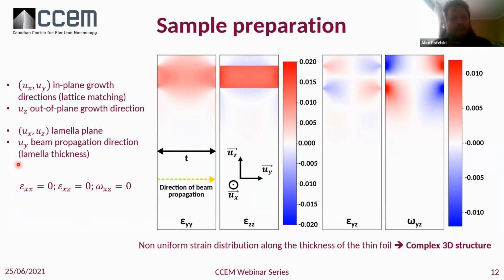As I told you, in plane along X, so perpendicular to the pillar, there is no deformation, no shear, no rotation. And we're going to use the following notation throughout the entire presentation. We're going to call UX and UY the in-plane growth directions, and UZ is going to be the out-of-plane direction regarding growth. UX UZ is going to be our lamellar plane, the one we're looking at when we do our TEM imaging. And UY is going to be the beam propagation direction, so the lamellar thickness. So along X, as I just told you, at 0 there is no deformation, so there is lattice matching.